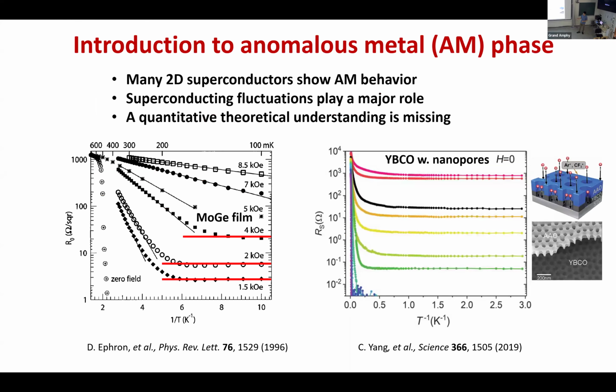So, anomalous metal phase. The feature of the anomalous metal phase is quite simple. When we measure the resistance during the superconducting transition, usually if you go to lower temperature, the resistance just drops to zero. And when you apply the field, the transition just shifts to lower temperature, but in the end, it should drop to zero. But for some systems, many 2D superconductors, the transition actually does not go to zero. It saturates at low temperature. So this is the feature that people claim to be the anomalous metal phase.